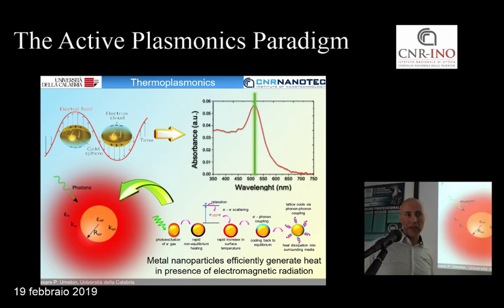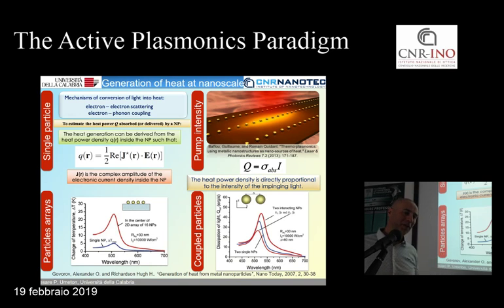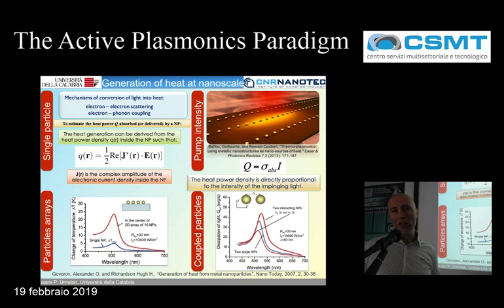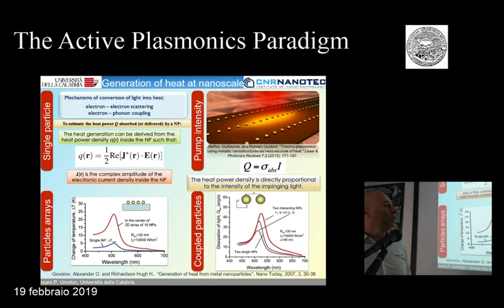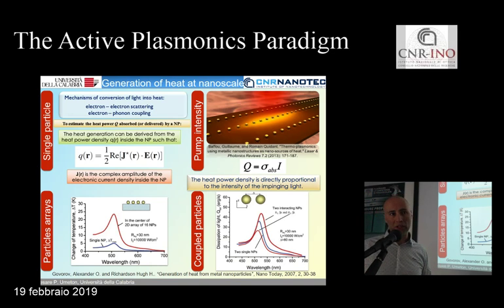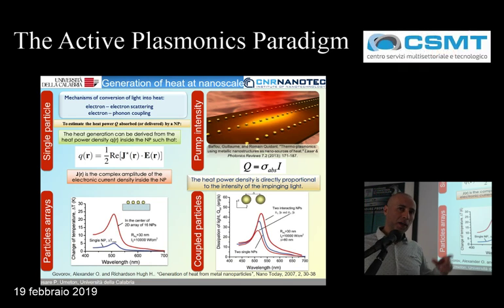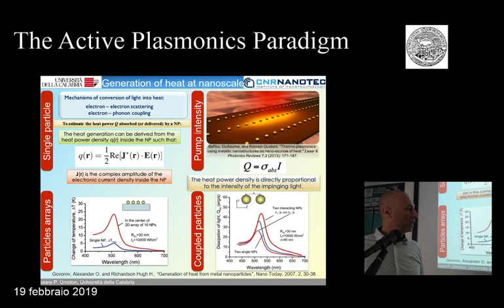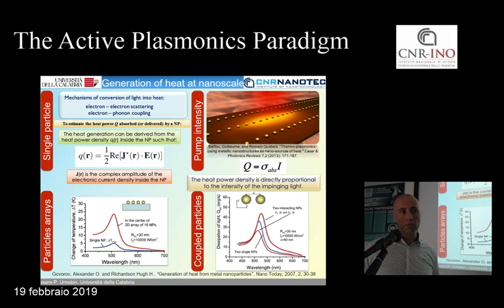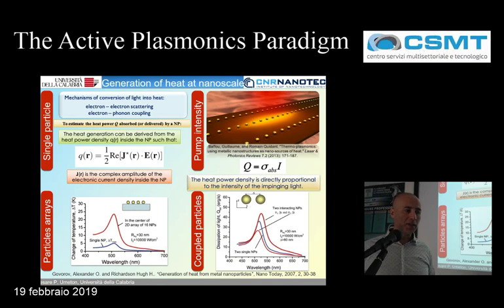We started working recently in this direction, and of course we needed to make some literature search before starting. And you can easily find that, okay, the single particle does not produce very much heat, but when you have many of them, you can easily maximize the effect because there is a collective thermal effect from the particles. But more interesting is that if you have coupled particles, like in the case we saw before during the stretching action, the result is much more efficient. So in principle, if by using deformation you induce a thermoplasmonic response by coupling, you can have a much bigger effect in terms of heat generation. And we tried to use this by considering the previous system just from a thermoplasmonic point of view.